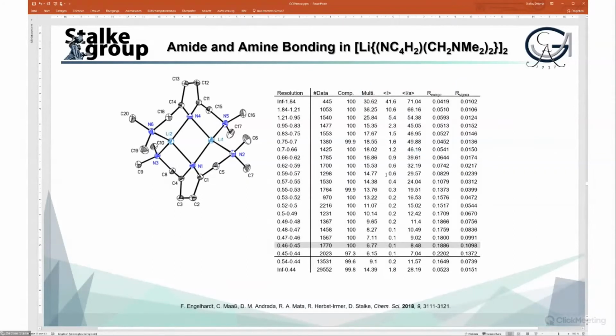So this is again the amount of data we're talking of. This is completeness, 100% up to the resolution of 0.45. Then we have multiplicity. I hate the expression of redundancy. Redundancy is no good. So what we need is multiplicity, right? We need every event to be observed as frequently as possible. And there is no point in driving your detector in an area where nothing happens, right?